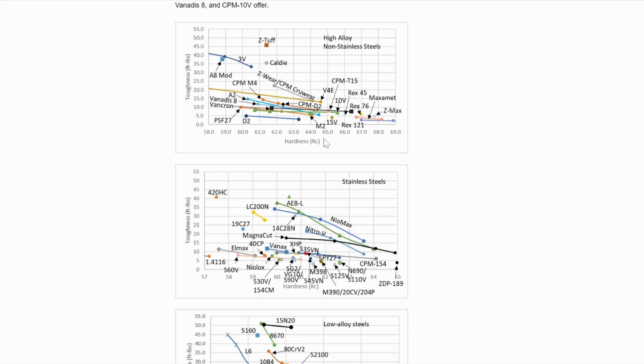Where Vanadis 4 Extra at 64.5 Rockwell can be 12 or 13 foot-pounds, not nearly to the point of its 20 foot-pounds at lower hardness. And then these high hardness steels, they just are all together the same. However, there are still differences. You can see CPM T15 or 10V are significantly tougher than 15V, for example. And even Rex 76 is tougher at 67 Rockwell than Maxamet or Rex 121.